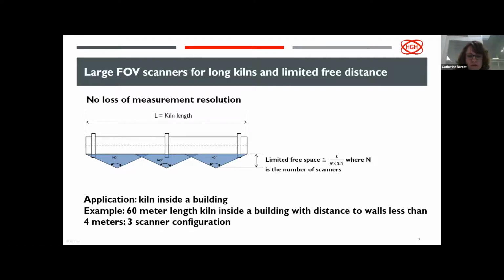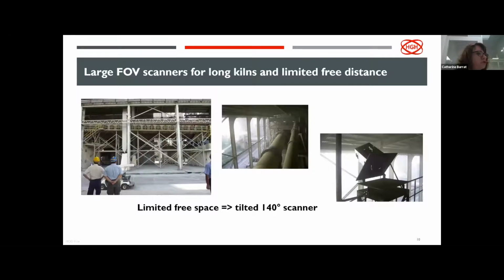This configuration is frequently installed when kilns are integrated into a building. We have such an installation shown here in this building, where we have a very limited free space. We used a tilted 140-degree angle field of view scanner located just under the roof of this installation, and being able to scan all along the kiln shell without any loss of resolution. I mean, without any loss of spatial resolution and without any loss of thermal resolution.